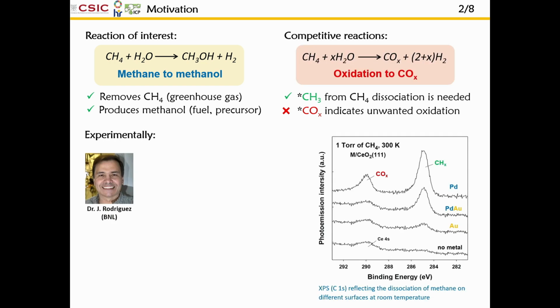So we also collaborate with the experimental group of José Rodríguez, and they found this XPS of carbon 1s, and these two peaks are precisely related to what I was telling you about. If you see this peak, it means that you have overoxidized methane and you lose selectivity, and if you don't have this peak, it means that you are not able to activate the molecule, so you are not doing anything.